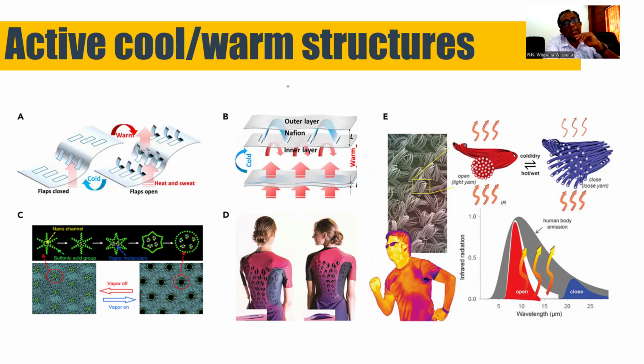And especially if you can make these cavities even smaller, into the nano cavities level, some other thermal phenomena will kick in. Especially if we take aerogel materials. Aerogel materials have very small cavities, very small. So even the phonons, the heat cannot really penetrate any. So heat gets blocked completely. Depending on the pore size and the pore geometry, special effects can also take place.